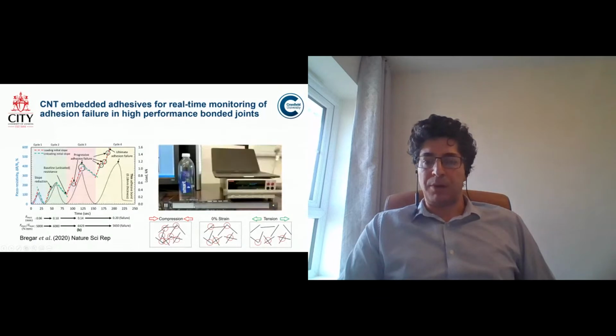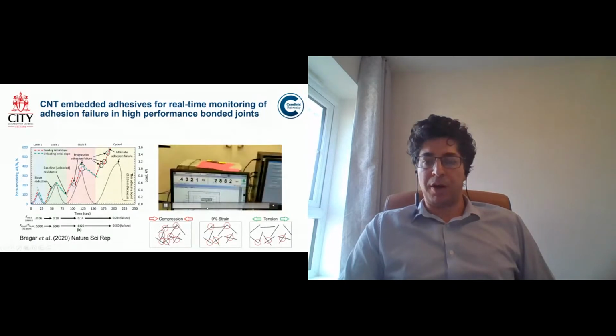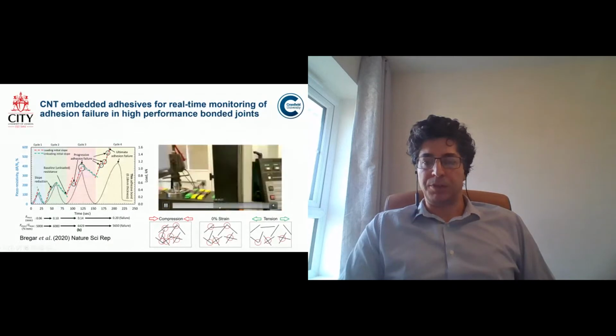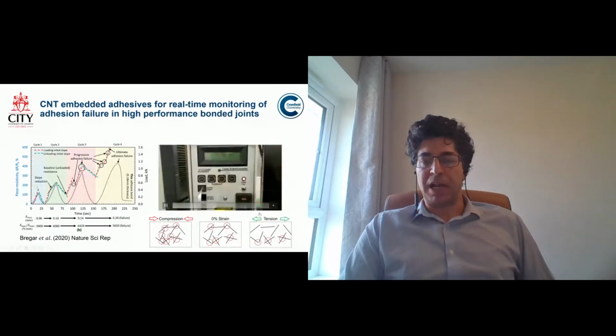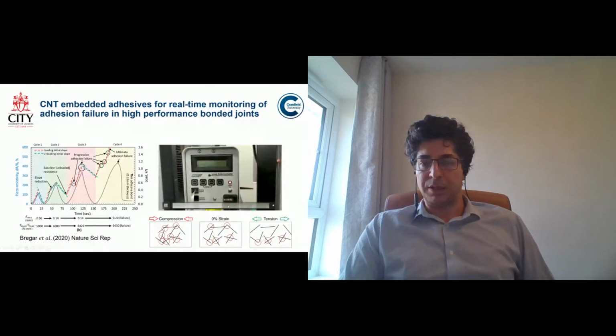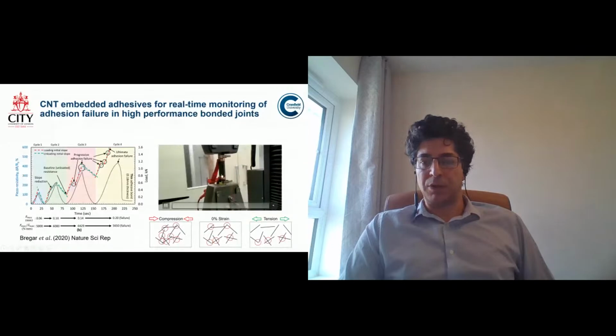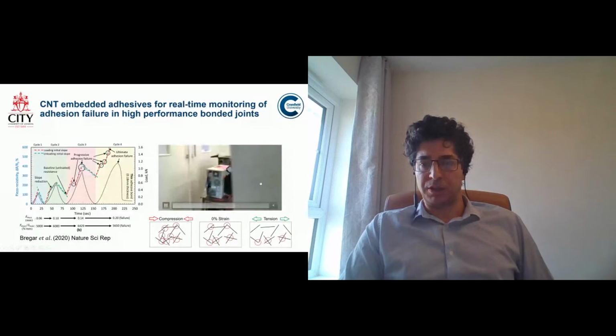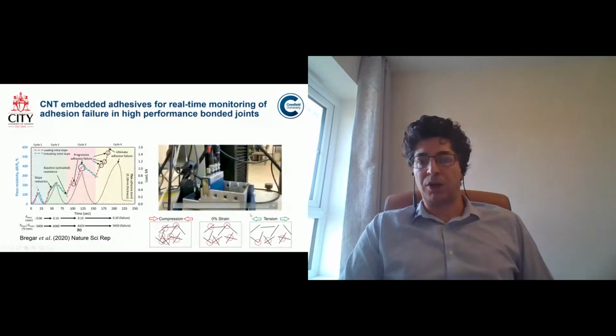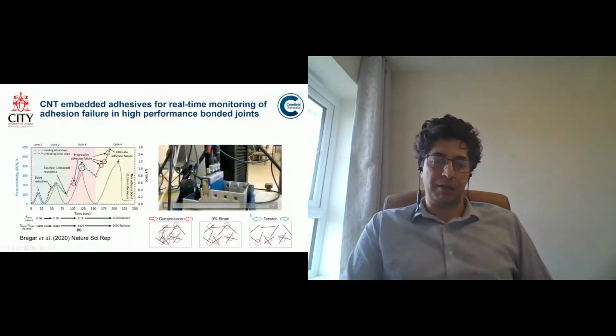That's the challenge we're talking about, when we still do a lot of wiring. Let me just move on for the time. So we use lots of facilities to validate this, like laser extensometers and in situ real-time measurement. That's where the smart specimen has been set up with a two-probe conductivity or resistivity measurement, and that's what I'm talking about. There are still loads of requirements for electronic accessories and algorithms, which in our case were written in LabVIEW. Thanks to Isidro and his group for helping us. But if that happens, the scale-up is very possible, very, very soon in the future.